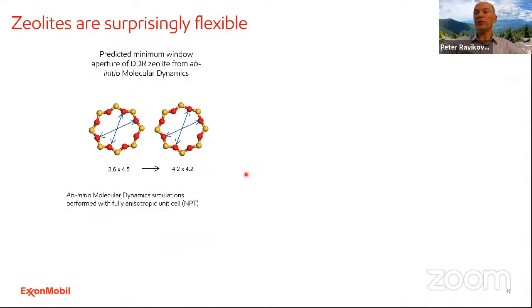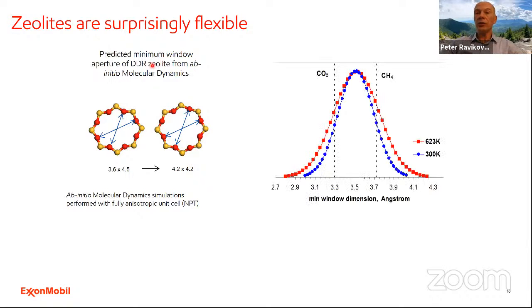Another complication is that zeolites are actually flexible. And if you do calculations, for example, so-called ab initio molecular dynamics calculations, we do not rely on the force field. It's basically molecular dynamics, but at every step you calculate your energies and forces using DFT. What you find is that the window, which is nominally crystallographically 3.6 by 4.5, actually changes all the time. And you can plot the so-called histogram of this minimum window dimension. And you can see that's a pretty broad histogram.